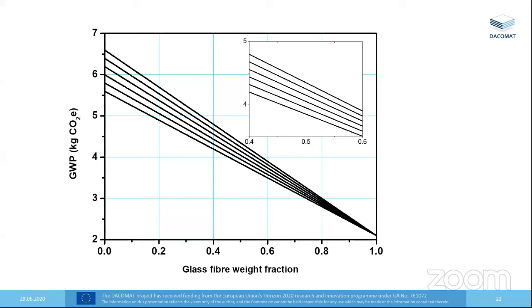Now this goes to ridiculous limits. It goes from a 0 weight fraction glass fibre, which isn't a composite, of course, it's just the resin, and it goes to a 1 weight fraction, which isn't a composite because it's just the glass fibre. But this basically encompasses the extremes, and somewhere within those extremes will be the actual composite that we manufacture. It might have a weight fraction of glass fibre of about 0.6, for example. So then we could look at these lines for our different vinyl ester resins. So again, we can look there and we can look at what the burdens are.